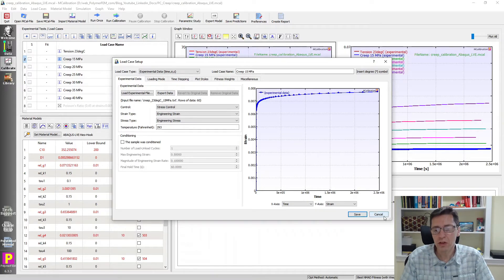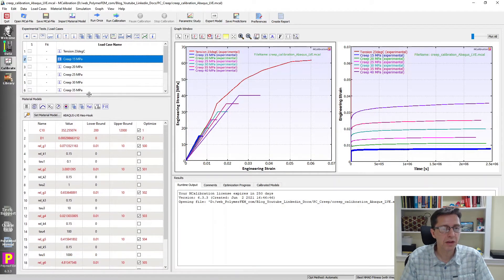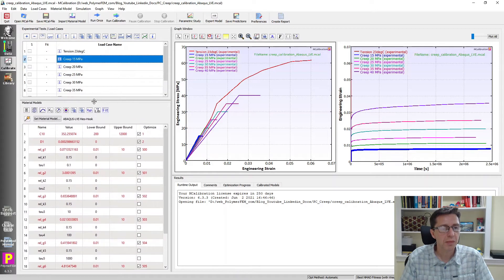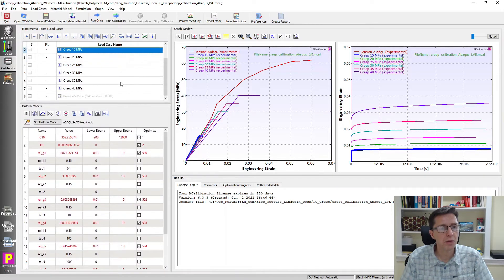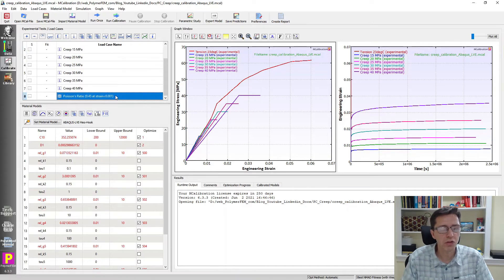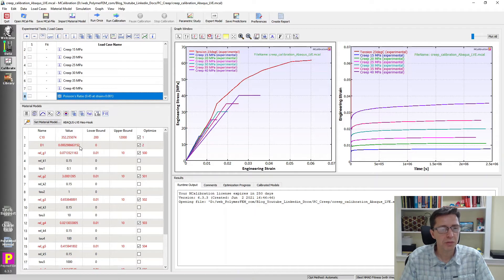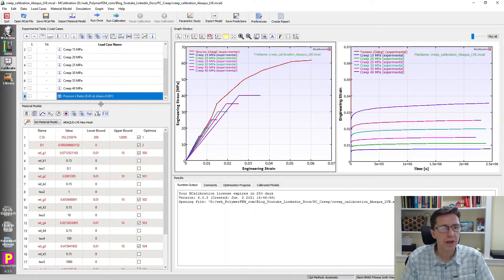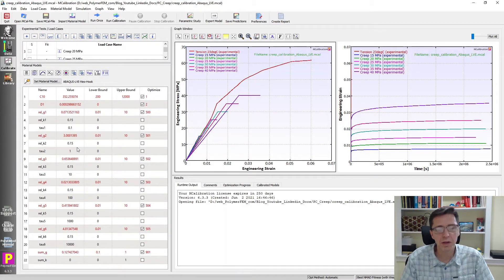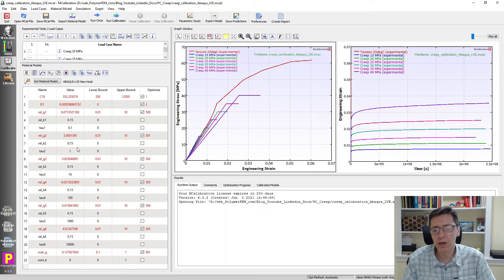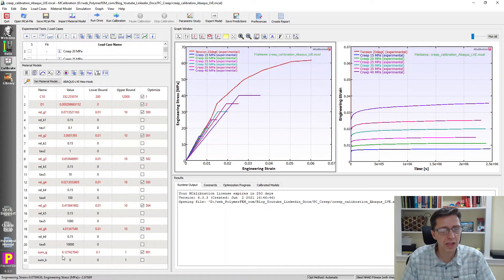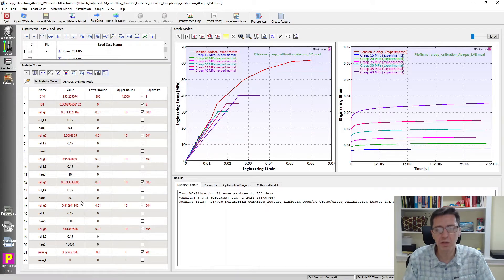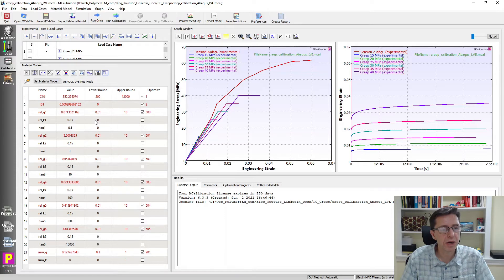So that's what I have here. I went ahead and picked a material. In this first case, I picked a linear viscoelastic Neo-Hookean material model. I did add a Poisson's ratio load case to calibrate the compressibility D1 parameter. When you have creep data, you've got to think carefully about what number of Prony series terms you use. I picked six in this case. It's a relatively small number, but it's good enough for predicting this response. I set the tau values to be reasonable based on the data and ran the calibration.